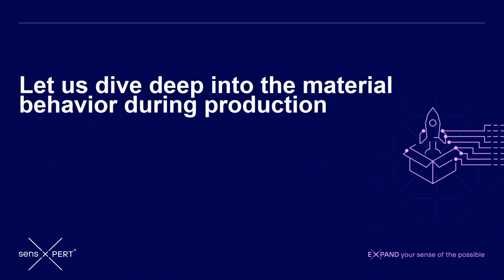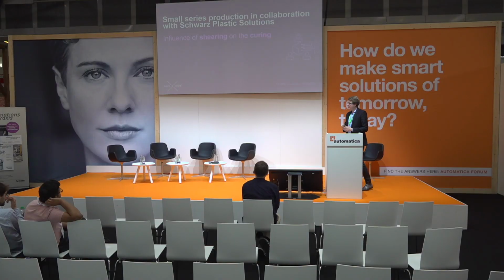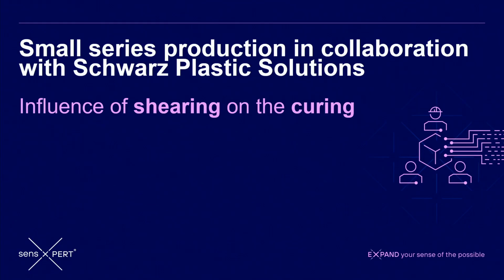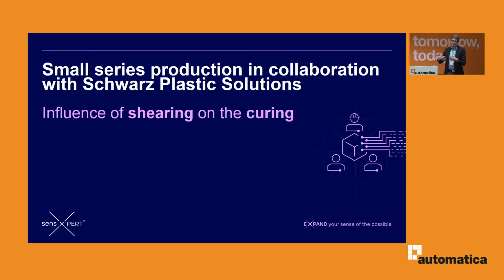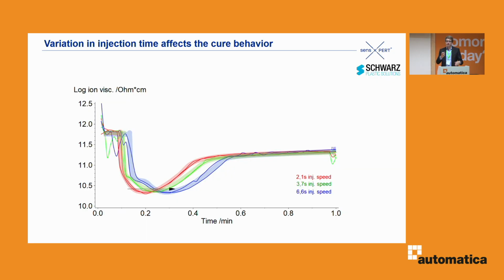I'd like to give you a really brief introduction into the material science of things, what it is that we actually detect. So one influence, for example, that we can have on the material is shearing. While we're producing the parts, the liquefied plastic is pressed through really thin channels from some kind of plasticizing unit into the actual cavity where the part is being formed. And during this flow process, the material is sheared, right? Parts of the material flow with different velocities, and that leads to shear.